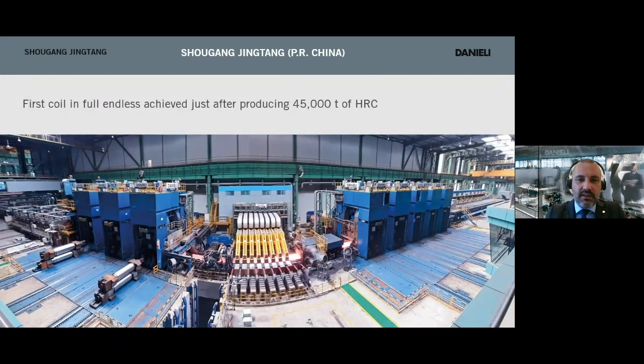Startup of the plant has been made in coil to coil. As soon as we got a consolidation of the coil to coil, we moved up to the development of semi-endless rolling, and finally the endless rolling has been implemented by getting the first coil after about 45,000 tons from hot roll coil hot test commencement.